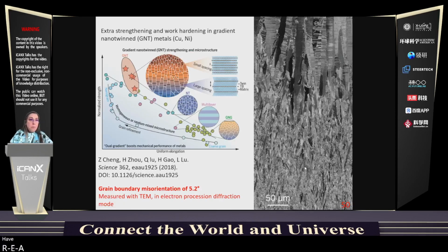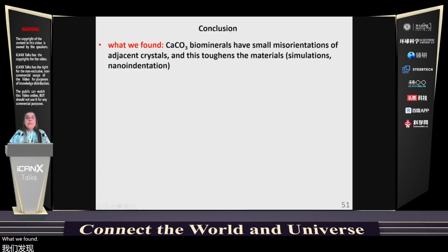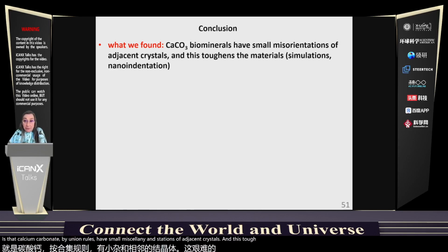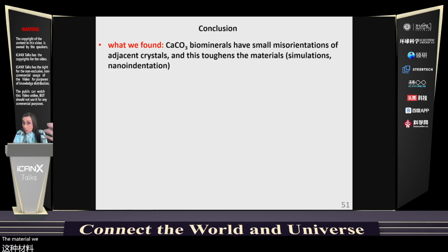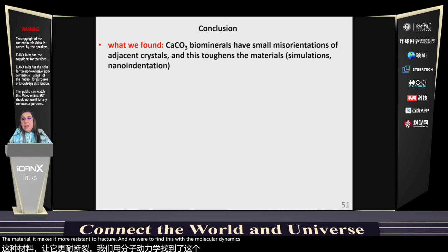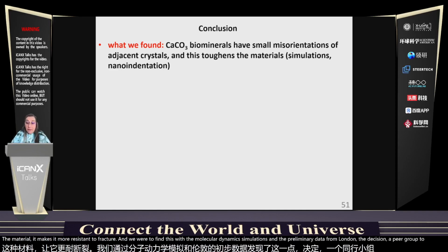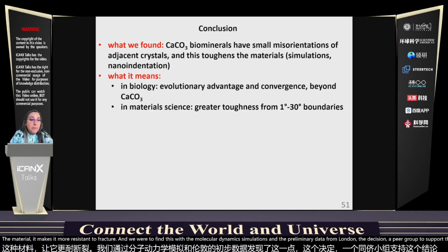I have 4 more minutes, so I'm gonna skip this and go to the conclusions. What we found is that calcium carbonate biominerals have small misorientations of adjacent crystals, and this toughens the material. It makes it more resistant to fracture, and we verified this with molecular dynamic simulations, and the preliminary data from nanoindentation appear to support that conclusion, that hypothesis.